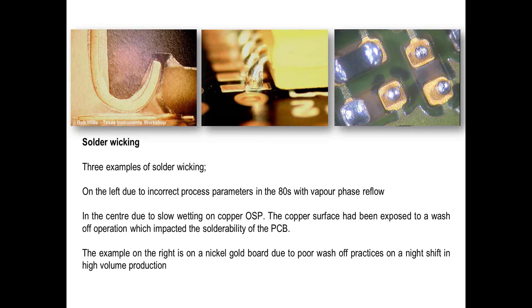But what in the process can we do to affect the wettability or solderability of the pad? Well, in the second example, in the middle of your screen, you're looking at a copper OSP board which went through a cleaning operation for side one assembly. Then when people went to side two, they had a problem, not of printing, but of reflow. The solder paste reflowed beautifully, but it all went up the pin. And that's an example of wicking.